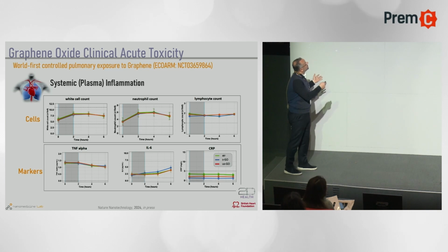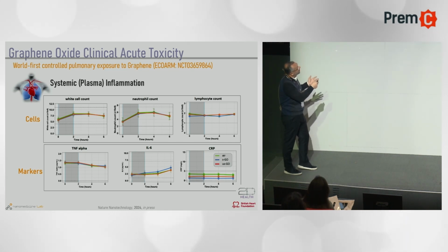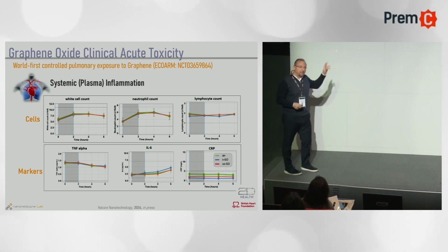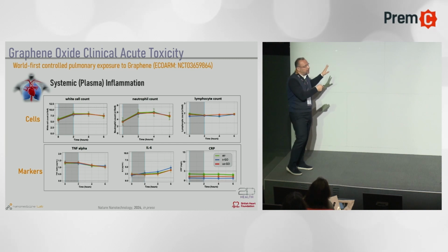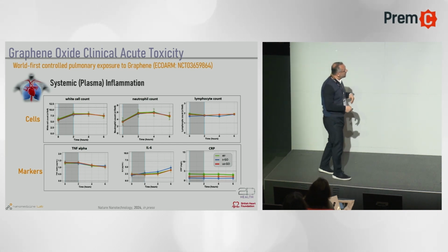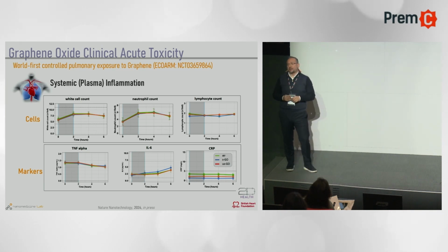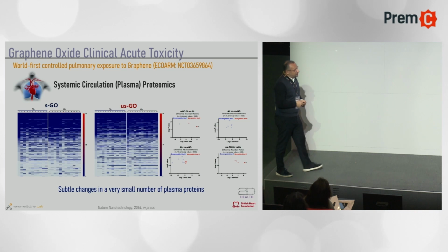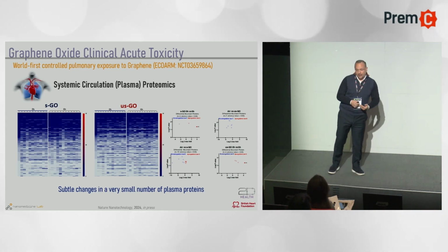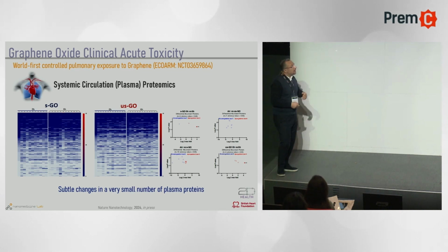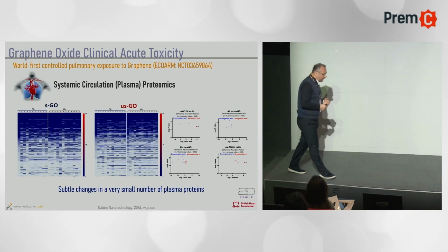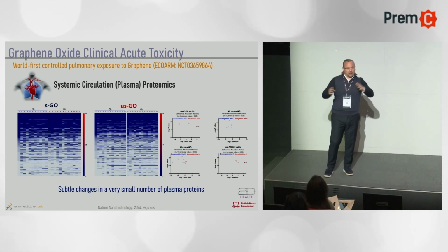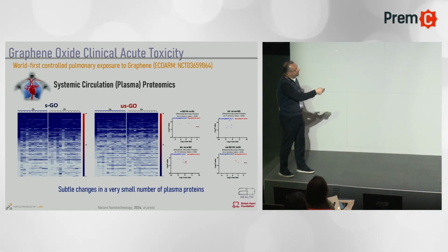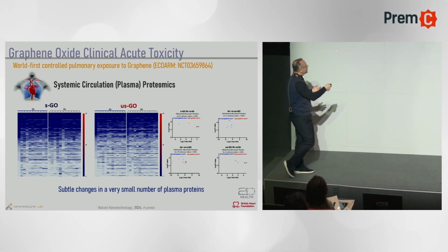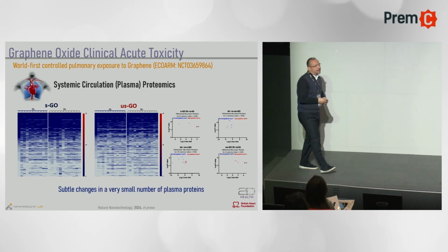The other thing we looked at was the systemic plasma inflammation, by looking at the number of cells and a few key markers. There are many more in the paper, but I'm just highlighting the usual suspects here: TNF-alpha, IL-6, and CRP. And you'll see again that we have almost physiological levels after the repeated exposures. We decided to go a little bit deeper into the proteomic analysis of these patients' blood samples, and we see again that we have very few changes. All these dots are the differentially abundant proteins that are either upregulated or downregulated post-exposure, and you'll see very few proteins that are changed compared to controls. So the conclusion here is, again, subtle changes in a very small number of plasma proteins.